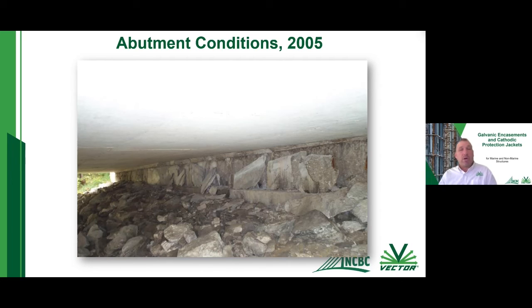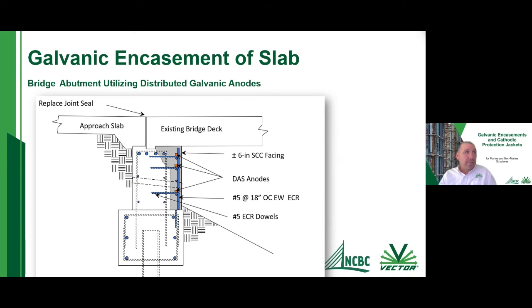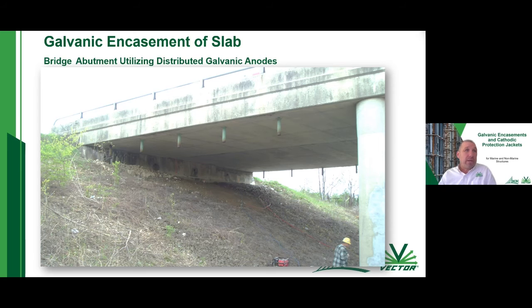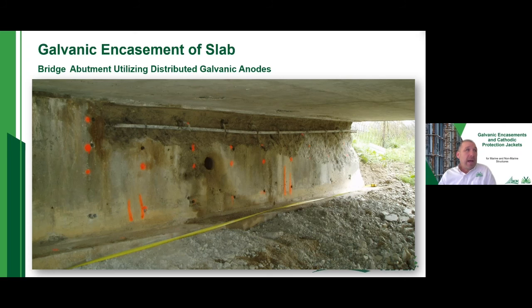So what we're going to do is something very, very similar to that atmospheric jacket that we used on piles. So all we're going to do is we're going to come in, and in this case, we're going to actually add some new reinforcement. So we're going to basically add kind of a structural cage of reinforcing steel. We're going to do an overbuild. And then on this overbuild, we're going to install these alkali activated anodes, which you can see there in the orange on this detail. So what they did was they came in. This was the structure just before they started working on it. They started to remove the delaminated concrete.